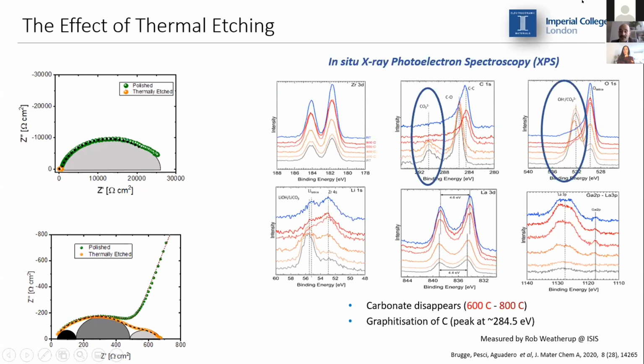The same thing we can see from the oxygen spectra, in which we also see a decrease and the disappearance of the oxygen peak associated with hydroxide and carbonates. Also, interestingly, we see a shift in the carbon-carbon peaks to lower binding energy, which can indicate a graphitization of carbon on the surface of our samples, and that can also have an effect on the electrochemical performance of garnet.